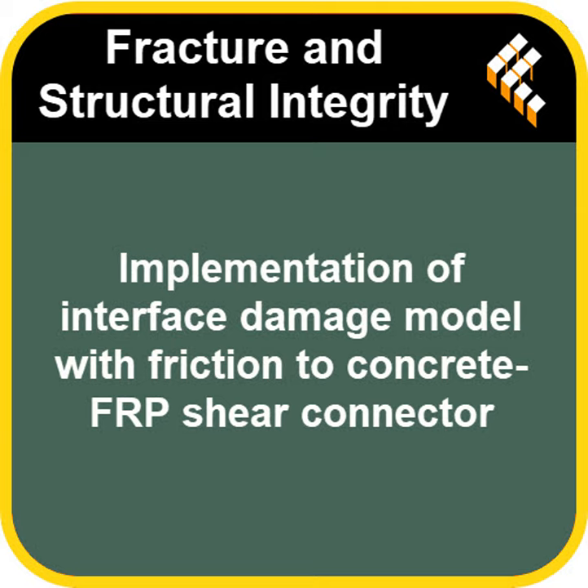Exactly. That's the fascinating part. Friction doesn't prevent the initial debonding, but it significantly helps the connector improve the load-bearing capacity. It lets the connector carry much more load even after the initial bond has started to fail. Think about this. With zero friction, the model showed the entire interface eventually debonding completely. But with friction, a good portion of the interface, especially in the area under compression, actually remained undamaged. That's a massive difference in behavior. Friction acts like a backup safety mechanism. That really changes how you might think about designing these.